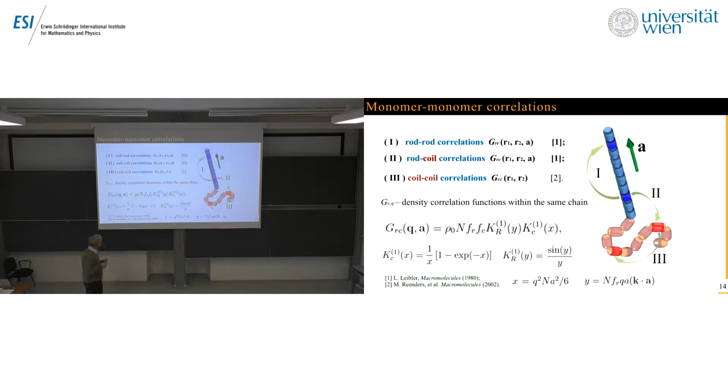So generally, these rod-coil correlation functions are orientationally dependent, and this is quite important because this contributes to the liquid crystal ordering. This is actually a coupling between the microphase separation effect, which creates this wave vector primarily, and the orientational order, which is partly induced by this part of the correlation function, on top of the standard effect determined by the Maier-Saupe interaction.